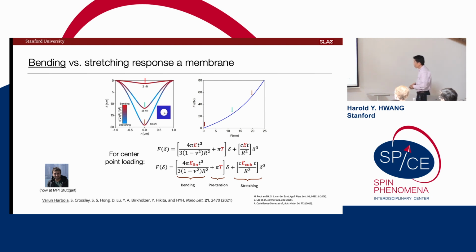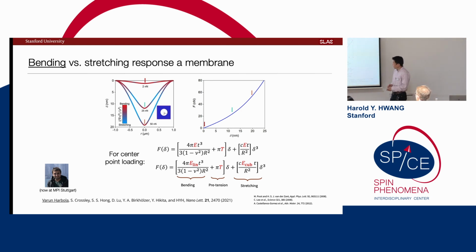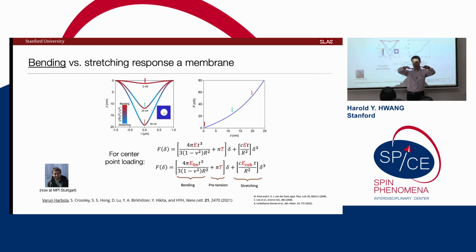Okay, so I will quickly summarize the first story where we find something definitively interesting or unexpected, let's say, coming from this gradient term. And that's, again, taking the things that people did playing with the nanomechanics of graphene. So this is a simple drum head. And these colors show you that if I poke in the middle of my drum head trampoline, the elastic energy initially is dominated by a bending response, right? It's the bending rigidity that's relevant. But if I poke harder and harder, more and more of that energy is coming from stretching the material in between.